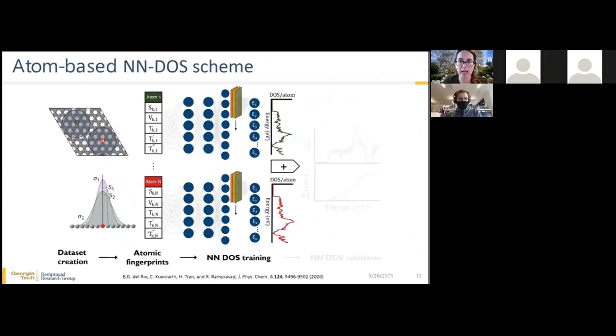And finally, once we have our model built, one thing is that this model that I show here, what it does is, as I said, we give as input the fingerprint of each atom. It goes through all these 5 layers, the convolutional layer, and gives as output the density of states for that atom. And then we give as input the other atom, and it goes through the same model and gives us output the density of states for that atom. And then what we do is sum all contributions, and then we obtain the total density of states.